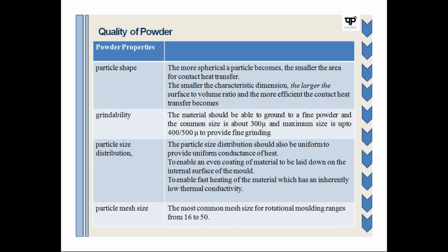and at most you can use 400 to 500. This basically depends on it: the finer the material, the better the fusion, right? So that particular part is going to affect the quality of the product. Another one is the particle size distribution, as I mentioned, at the time of converting from granule to powder, and the particle size distribution should be more uniform. Otherwise, it is going to cause a problem as far as the fusibility of the material is concerned, or maybe the sintering of the material inside the mold.